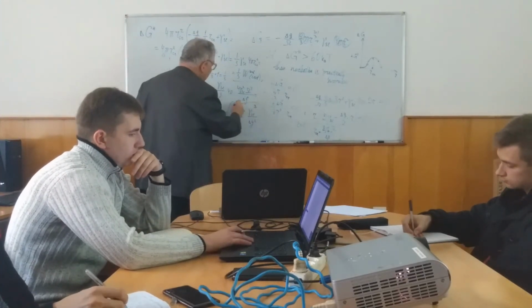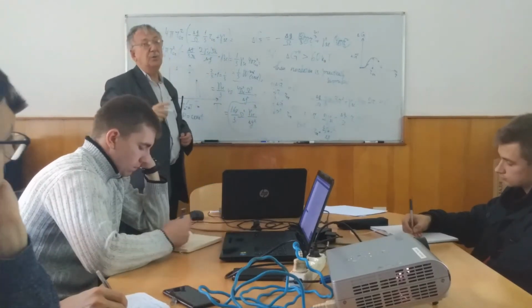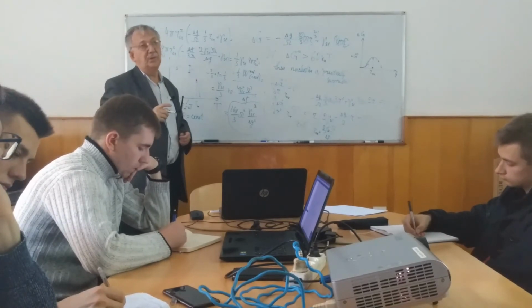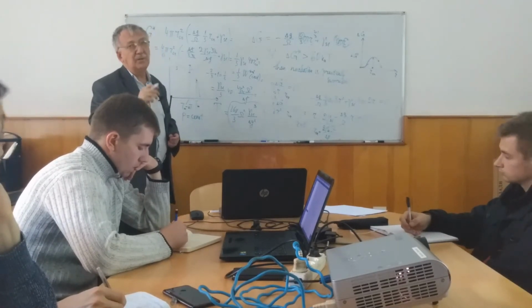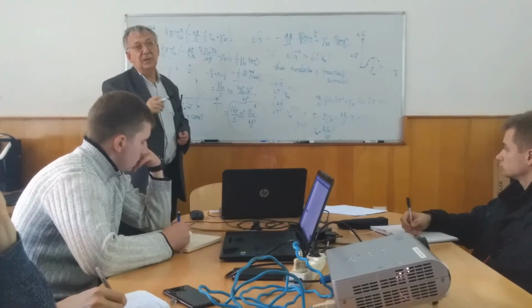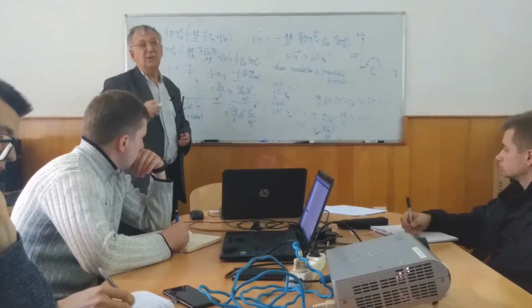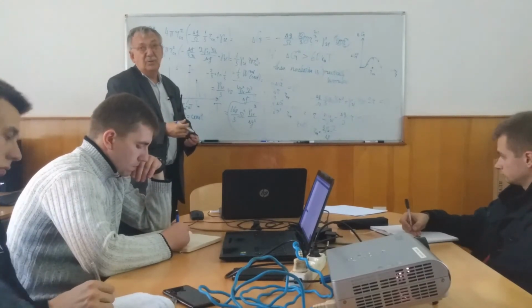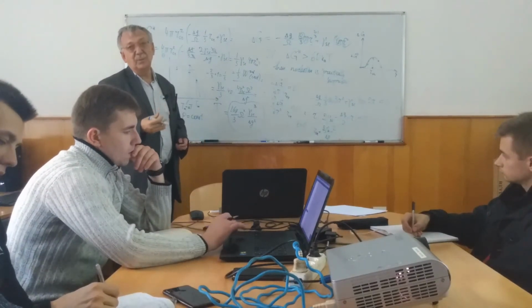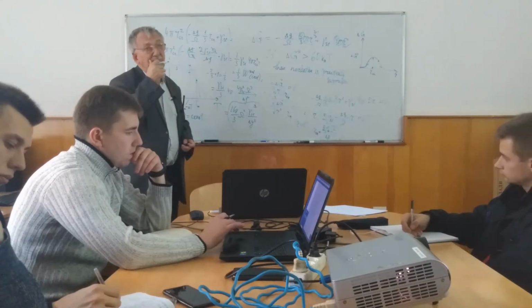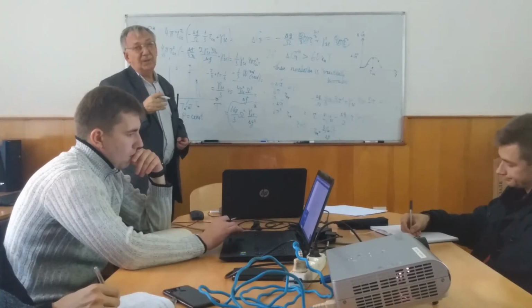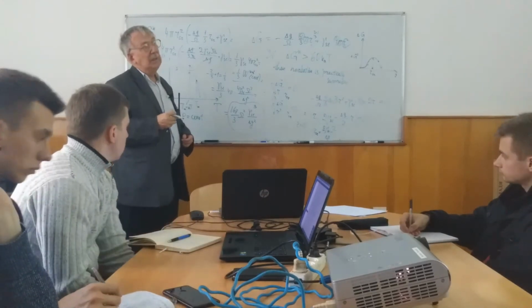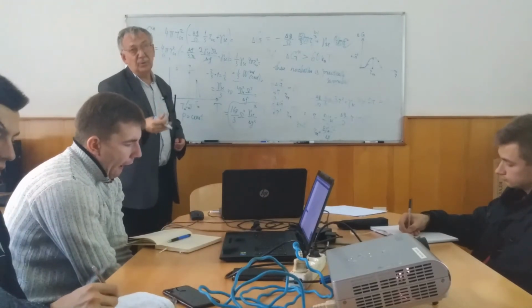This is the result, I remind you, for homogeneous nucleation, which almost never happens. Only in very pure and very small droplets of liquid in special experiments, which is not so easy to realize. But nevertheless, theoretically, we should start from this theoretically simplest, but experimentally very difficult situation, because it's a very difficult problem to avoid heterogeneous nucleation. We'll talk about this in a few minutes.